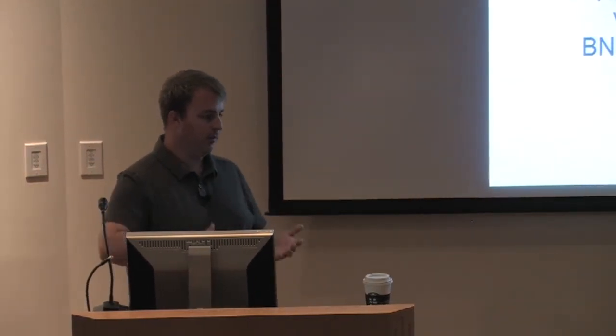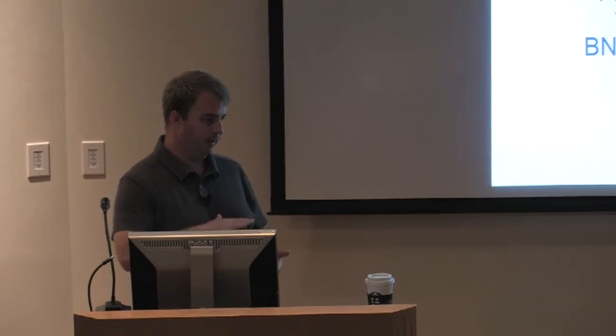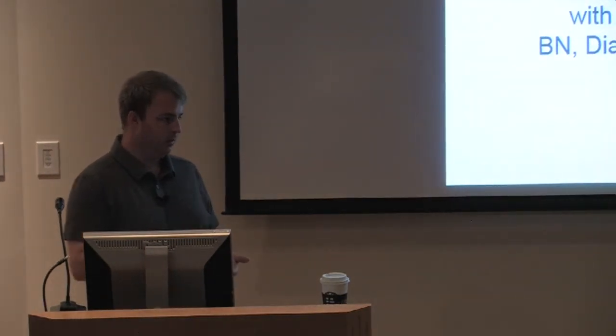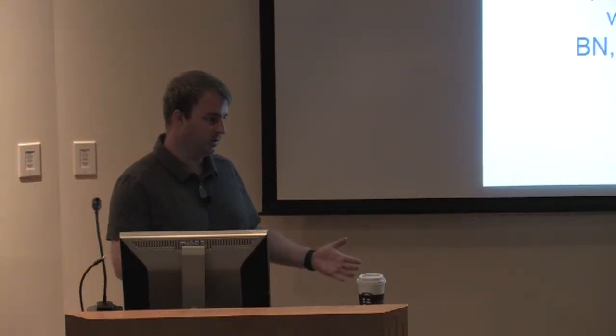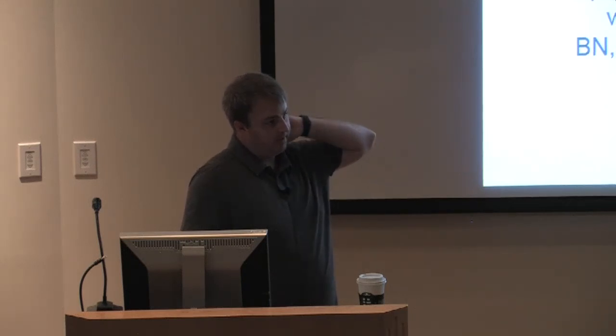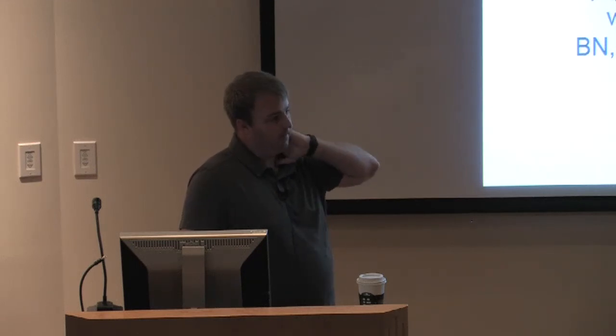Now, if you want to be at 1 or 2 degrees, you're probably okay, and you can work that way. You want to be very careful that you've prepared a nice, smooth surface, as smooth as you can. But if you want to work at really low angles, for a bulk powder like this, it doesn't really work because the roughness just kind of kills you. But yes, one of the zero background plates could definitely work for a grazing incidence at a few degrees. That would be a good way to go.